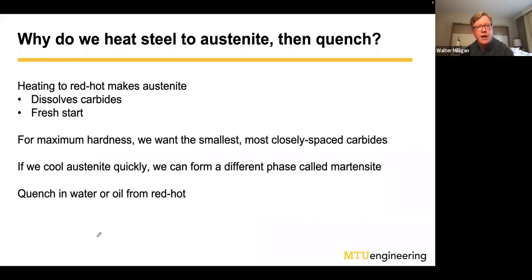So why do we heat the steel to austenite and then quench? I explained on the last slide that if we heat it up to the austenite phase, we can dissolve the carbides and get a fresh start with our microstructure. It turns out that for maximum hardness, as I said before, we want to have the smallest, most closely spaced carbide particles possible. And we can do that if we quench the material very, very quickly from austenite.